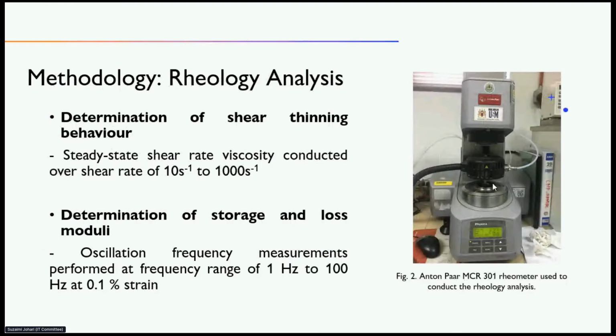The fourth part is the rheology analysis. So rheology analysis is important in bioprinting because it gives us an idea of how the bioink will respond and to see if it's actually suitable for extrusion bioprinting. There were 2 parameters that we tested. First is the shear thinning behavior. Second is the storage and loss modulus. And this is tested with the Anton Paar rheometer.